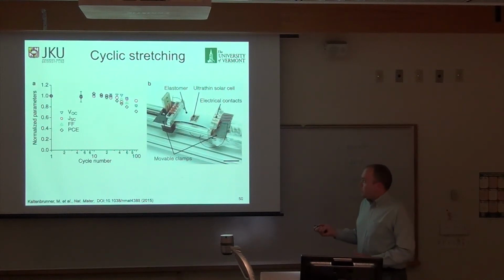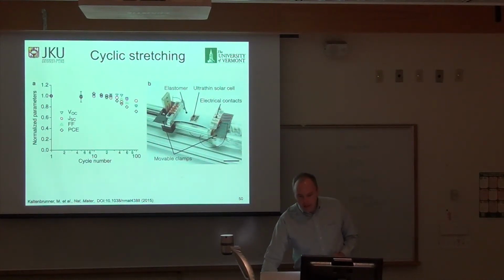These solar cells, you can stretch them, but how many times? Well, we stretched it with an automatic stretcher, up to 100 times, and after a while they do start to die, but that's probably just due to micro cracks forming in the metal electrode. We're not exactly sure what the primary mechanism is, but I would suspect it's cracking of the metal.